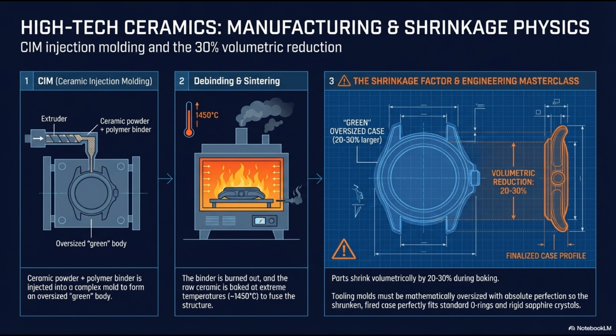Step 2 is debinding and sintering. The fragile green body is placed in an industrial furnace. Slowly, the polymer binder is burned out entirely. Then, the furnace is ramped up to extreme temperatures around 1450 degrees Celsius. At this heat, the raw ceramic powder particles literally fuse and weld together at the atomic level, creating the final, ultra-dense crystalline structure. But look at step 3, the shrinkage factor.